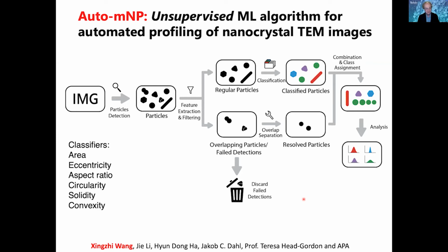The circularity, the solidity. And in our case, we are only going to do this for convex particles. There are, of course, many concave particles. We're developing a different approach towards that. But at the moment, this is only for convex nanoparticles. And so we have this series of classifiers, and we take all of these particles, and we do a kind of extraction of the particles to avoid ones which are overlapped from each other.